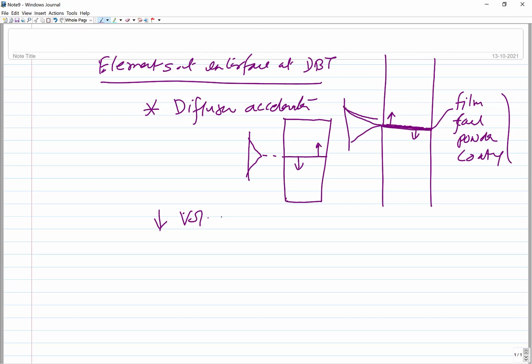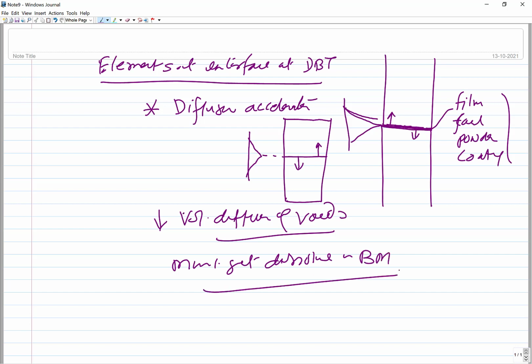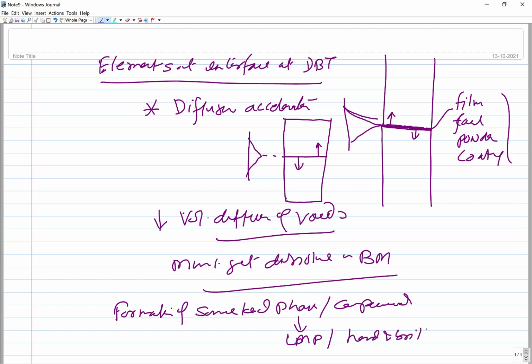That's what you can say, the volume diffusion of voids present at the interface is facilitated by this diffusion. Another important thing, these diffusion accelerators must get dissolved in the base metal, and if these are not getting dissolved, then you will find that these are leading to the formation of some kind of phase or compound, and presence of these phases or compounds may be of low melting point. This is one. These can be hard and brittle, so leading to the partial melting.